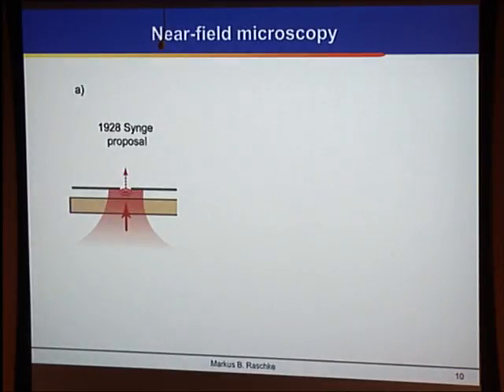Maybe a few more words on the history of it. The early idea of confining light to sub-diffraction dimensions came from the Irish, self-educated scientist who proposed it in a letter to Einstein: what if I take a small aperture, put it in my diffraction-limited focus, capture the light which emerges out of this aperture, and then move this aperture around? He recognized correctly that you have to put this aperture close to the sample, to first order by a distance given by the aperture diameter.